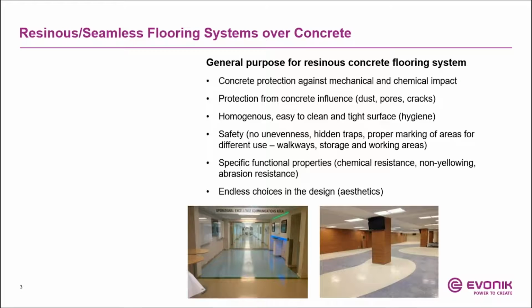Another reason is to protect from the influence of concrete. Over time, concrete can form dust, and also concrete is a porous material. So now you have moisture vapor coming up to the surface, bringing up some soluble salts. So now you have efflorescence on the surface of the concrete. Another is, through thermal expansion and contraction, you have cracks forming on the concrete surface. So by applying a coating on top of the concrete, you're really protecting from the influence of the concrete. The third reason is that forming a homogeneous coating on the surface of the concrete makes it easy to clean. So there are no places, no crevices and other things, for bacteria or microbes to grow. So it makes it easy to clean, and again, you have a nice hygienic space.